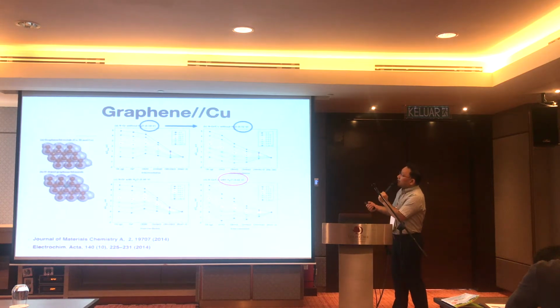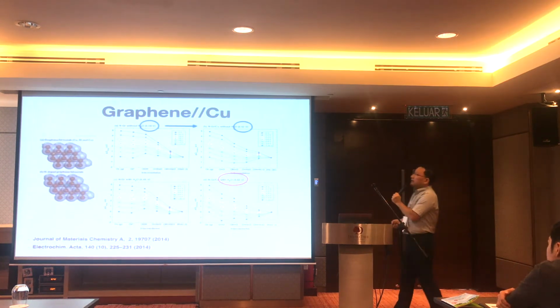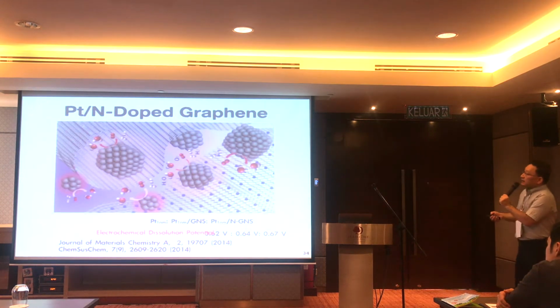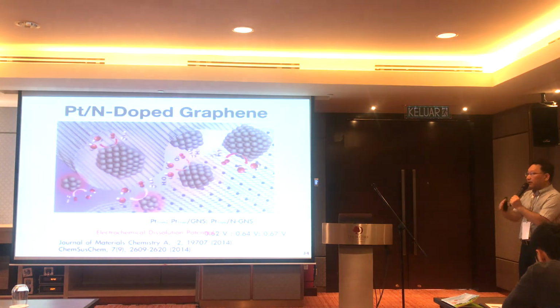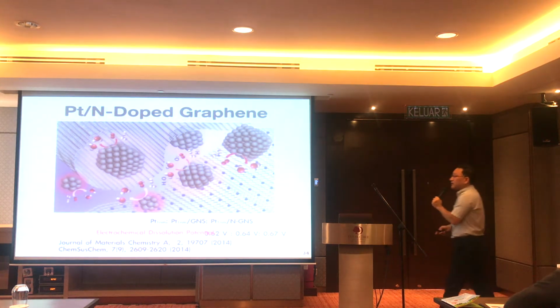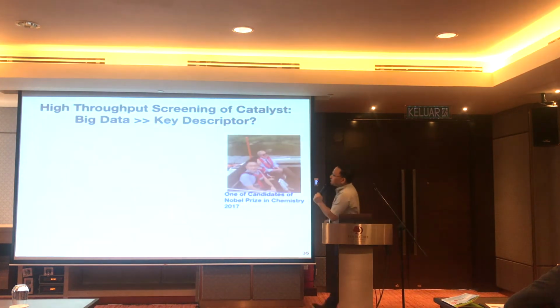How about graphene overlaid by copper? They are good, but copper is not good whenever there is water. It easily oxidizes. So we tried many times. But how about graphene used as a blanket to enhance the dissolution potential of platinum? Maybe if you cover a platinum nanoparticle like that, you can trap platinum from dissolution. But what he found was that the dissolution potential enhancement is 15 millivolts. So forget about graphenes.